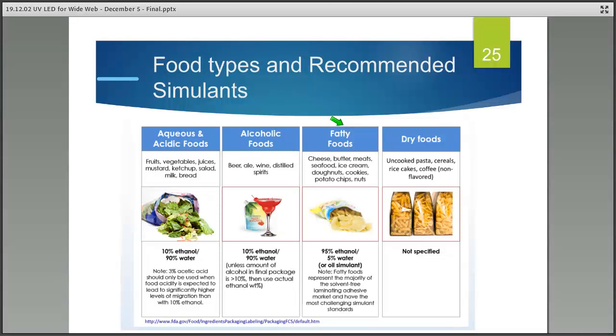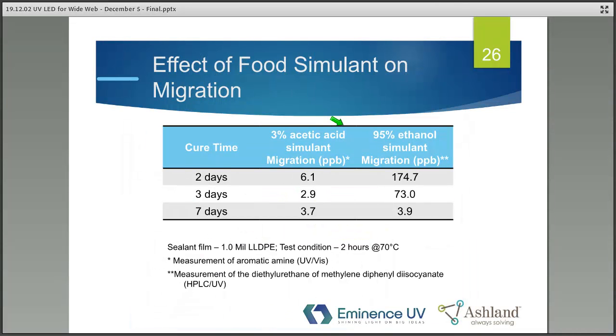So what are the effects of the food simulants on migration? In this slide, this is not an LED material. This is a material that was used in a laminating adhesive. It's an aromatic isocyanate, and I'm demonstrating the migration of aromatic isocyanate in a fatty food simulant, which is 95% ethanol, and an aqueous food simulant, which is 3% acetic acid. Cure time is not relevant for LED; you actually have to cure these things over time for the laminating adhesives. But what you can see clearly is that in aqueous food simulant, you have much lower migration compared to a fatty food simulant.